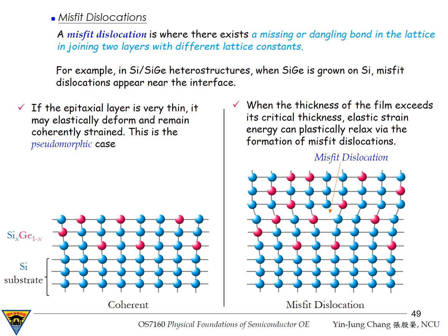When a silicon germanium layer is first grown on silicon, the film initially grows pseudomorphically, meaning it is compressed laterally to match the silicon lattice. But once the film thickness exceeds a certain value, called the critical thickness, the strain energy becomes large enough that the system lowers its total energy by forming misfit dislocations at the interface, as shown here.